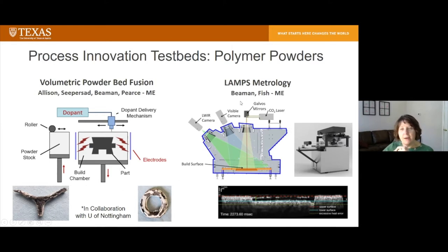On the right, you can see one of our higher TRL level test beds. This was developed by Joe Beaman and Scott Fish and their collaborators. And this is a completely open hardware, open software laser sintering machine. It's capable of higher temperatures than most polymer machines, and it's fully instrumented. Here you can see an infrared camera, a visible camera. They've also outfitted it with OCT as well. And there's an image on the bottom there of an OCT scan of the powder bed, and you can start to see under the surface. They use this type of information to provide intelligent feedback control to the process so that they can adjust it to get better parts with better geometric and mechanical accuracy.